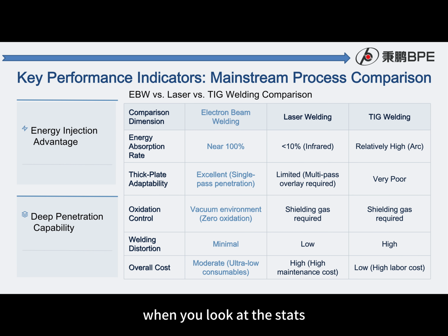When you look at the stats, it's night and day, nearly 100% absorption for EBW versus under 10% for infrared lasers. EBW wins across the board in penetration depth, thick plate performance, distortion control, and oxidation prevention. For deep penetration copper, it's clearly the superior choice.